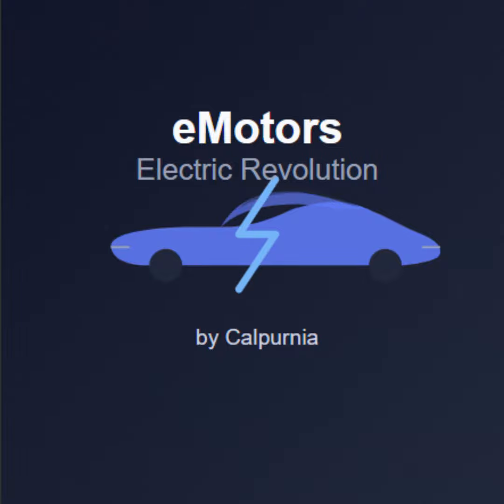Ah, so it's not the driving, it's the charging needed to enable the driving. Exactly. If a high-use driver, maybe a taxi or a delivery van, can consistently recharge using gentle overnight level 2 AC charging, the rate of battery degradation actually approaches that of a low-use vehicle that's charged the same way. So the key takeaway here is actually quite positive for using EVs. High vehicle utilization is great. It's encouraged even, to maximize the economic benefits and reduce the total cost of ownership. You just need to optimize the charging methods to avoid that daily reliance on high-stress fast chargers whenever possible.